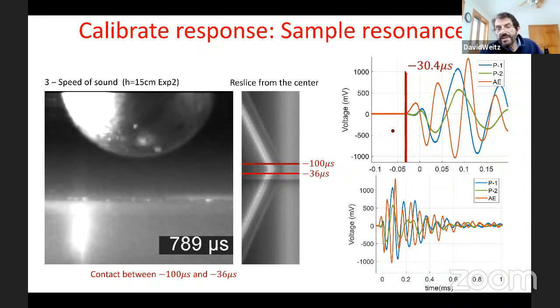And we can measure the response of the sensors. We see this ringing response, and we're pretty sure that the ringing response is just that we're exciting some vibration or some resonance of the whole sample itself. This is consistent with the speed of sound and the size of the sample.